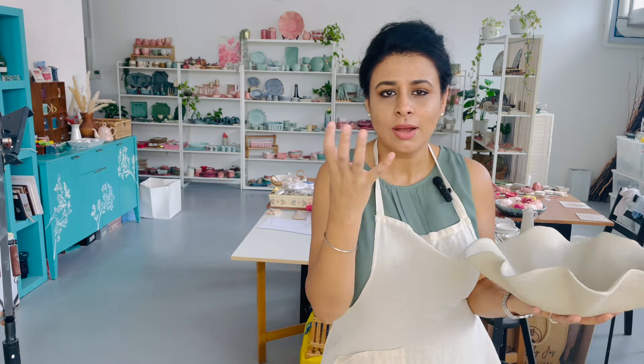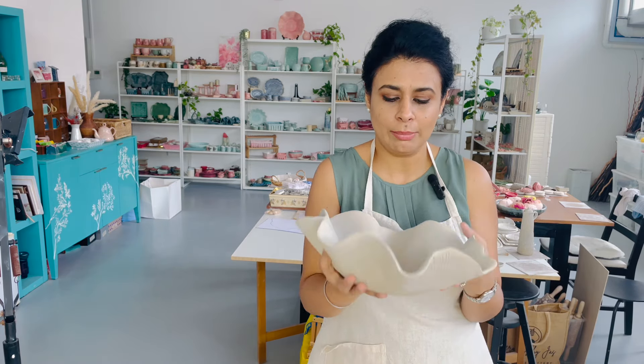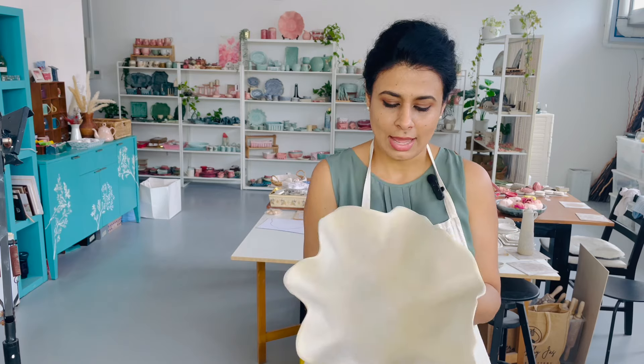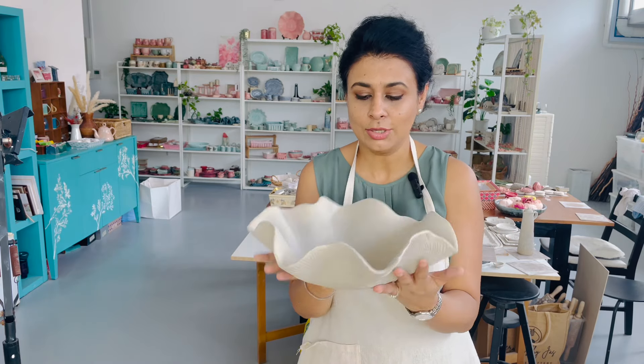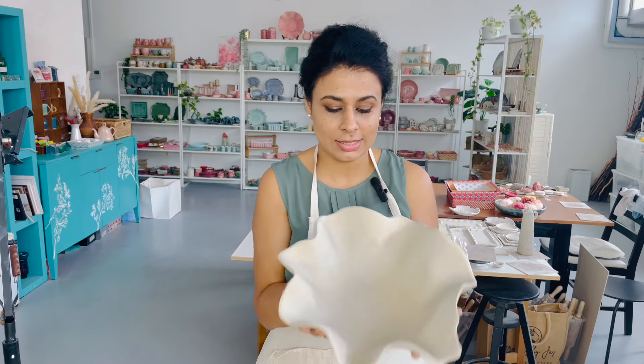The most important thing is even drying. Once it's completely dry, I will put it through bisque fire. I bisque fire at about 950 degrees Celsius, and the last stage will be glazing — I'll probably record the entire process and share it once it's at that stage. But for now, this is what we have.